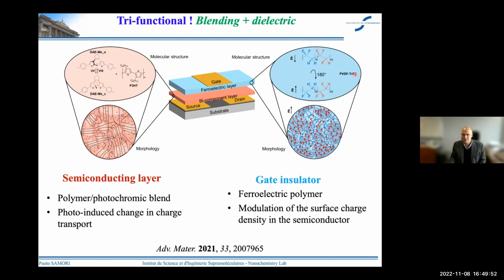PVDF-TrFE, polyvinylidene fluoride trifluoroethylene, which is known to have a relatively large fatigue-free remnant polarization, a short switching time, and good thermal stability. The ferroelectric state of the gate insulator will influence the surface potential of the interface with the semiconductor, and in this way the accumulation or depletion state of the charge in the device. So in this case too, we can store information in a non-volatile manner. And that is the cartoon of our device.